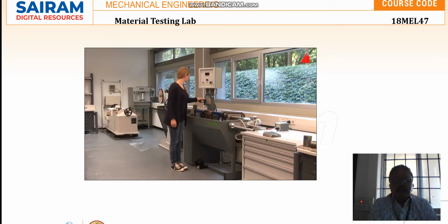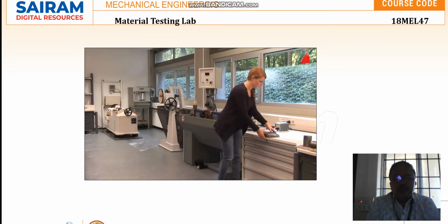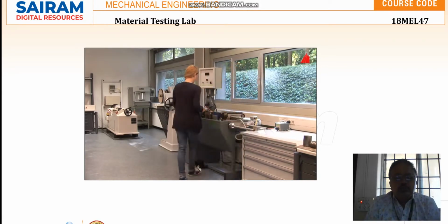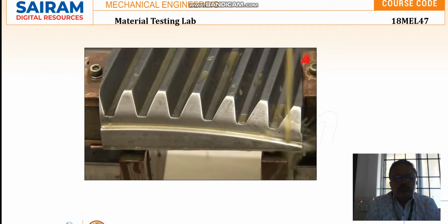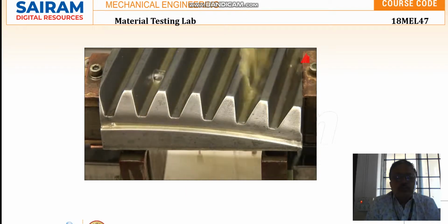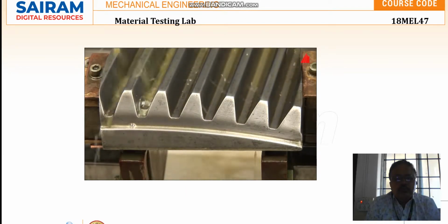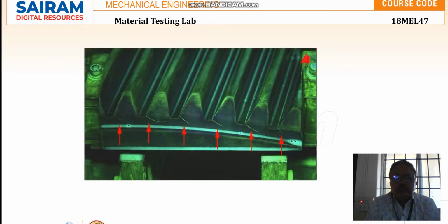Still another test piece has to face the magnetic particle inspection, a section of a large gear wheel. The same procedure again. Placing the gear wheel between the magnetic pole pieces, magnetizing and applying magnetic particle suspension. Already in daylight, there are indications of cracks, and again, they are best visible under ultraviolet light while darkening the daylight. The visible cracks are so-called fatigue cracks.